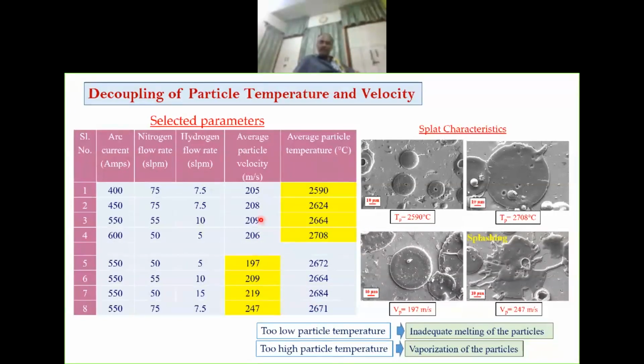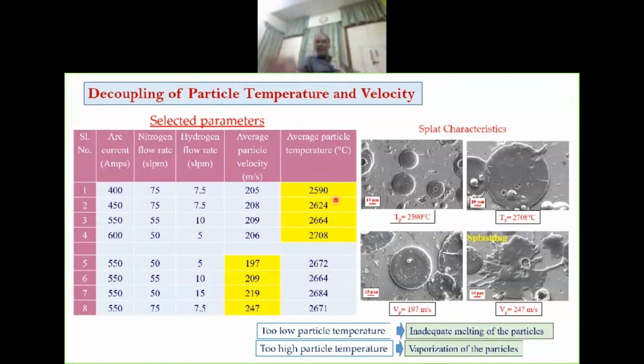It was made possible by rigorous experimentation. Have a look at the velocity and temperature. Temperature. If you increase temperature, you'll melt it. Too low a temperature will leave the particle unmelted. But if you go too high, well, you are wasting heat, number one. And number two is that for low melting point particles, some particles can vaporize. We can give a particle temperature of 3000. We don't need a temperature of 3000 for melting iron or nickel. Forget about copper or aluminium. So deposition efficiency will fall if you insist on too high a temperature.